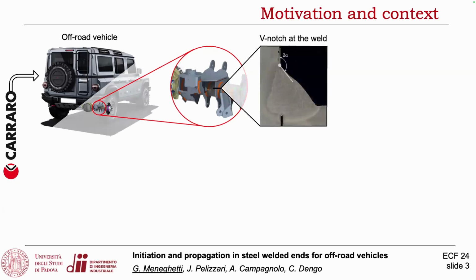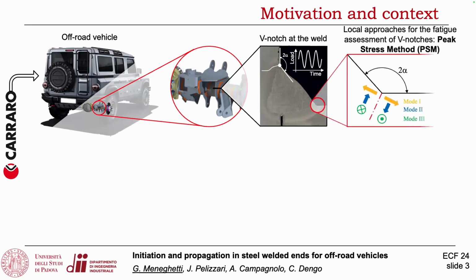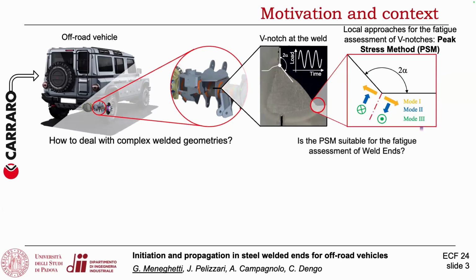With that in mind, we were asked to apply the local approach, and we studied the fatigue lifetime of such structures using the peak stress method. The basic idea is to take into account the sharp V-notches at the weld toe or the weld root, and define an appropriate design stress.